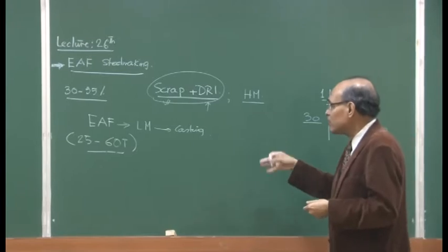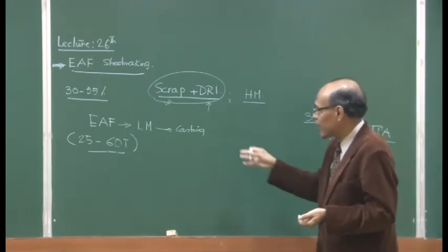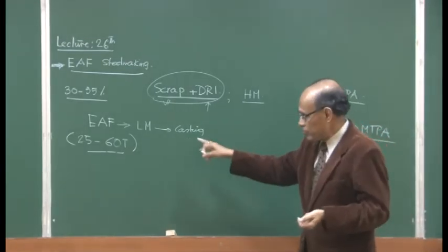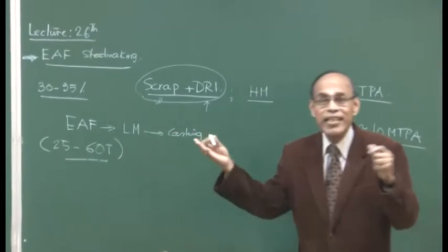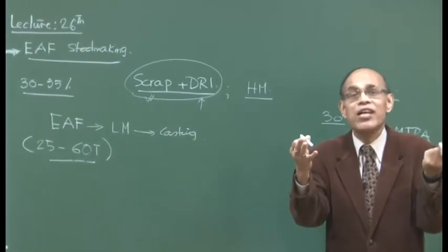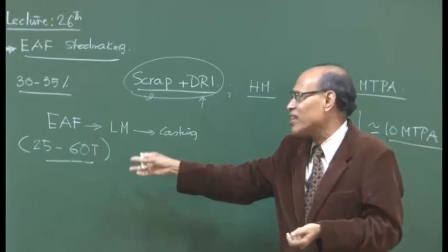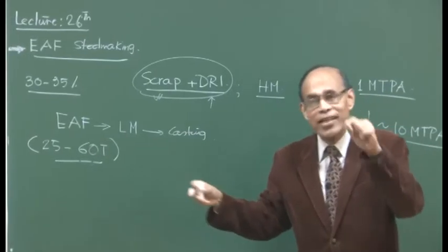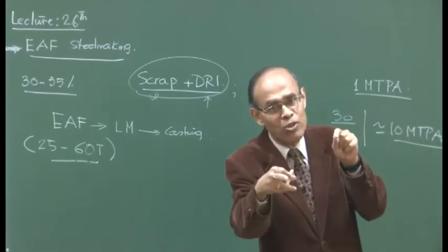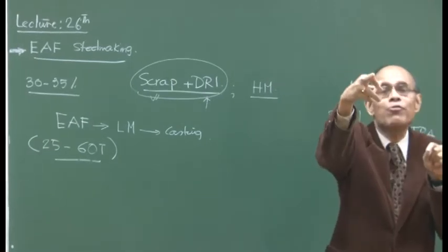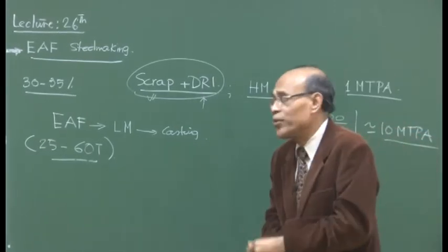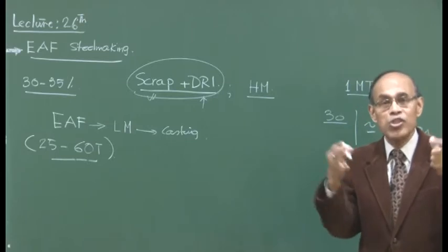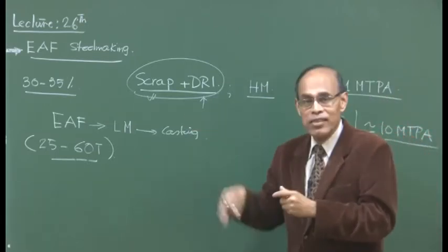The reactor maybe 1.5, 1.8, something like that. And so the nature of the chemical reactions, the carbon oxygen reactions, we will write the same set of carbon oxygen reactions even for steel making. Either dissolved carbon will react with dissolved oxygen, or dissolved carbon will react with FeO content in the slag. So, these are the two dominant mechanisms of carbon oxidation in BOF as well.